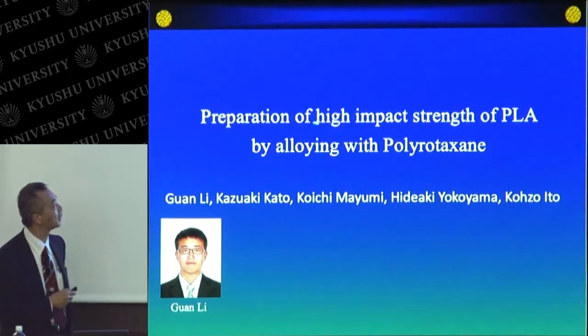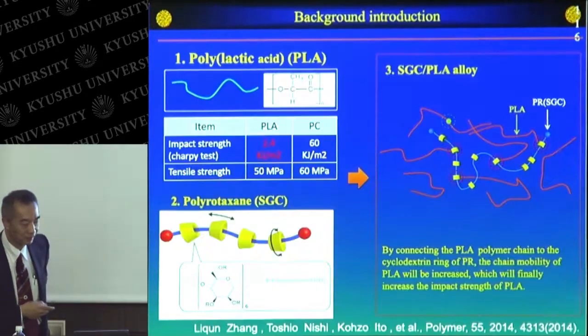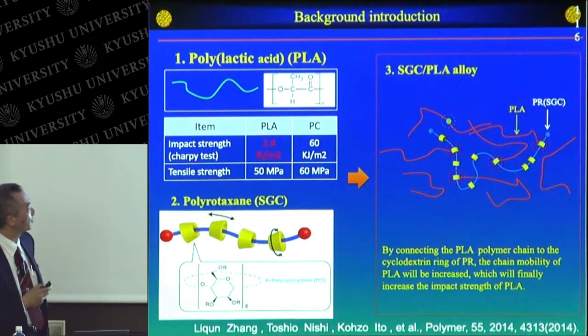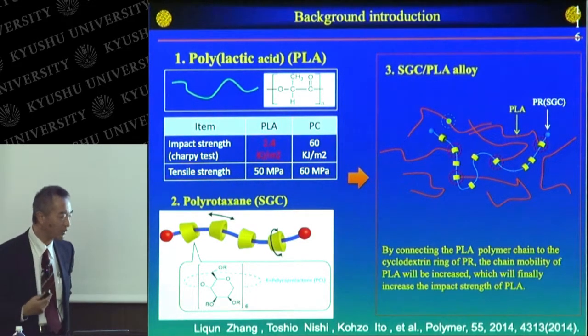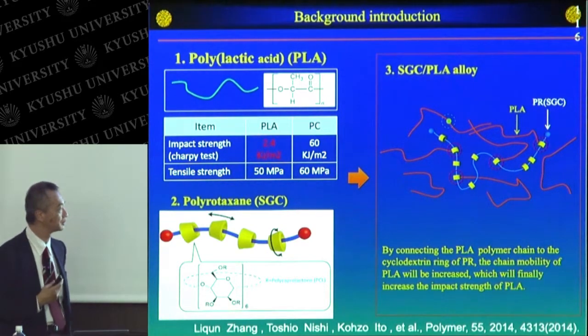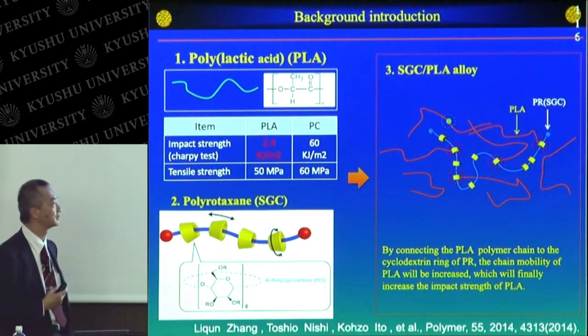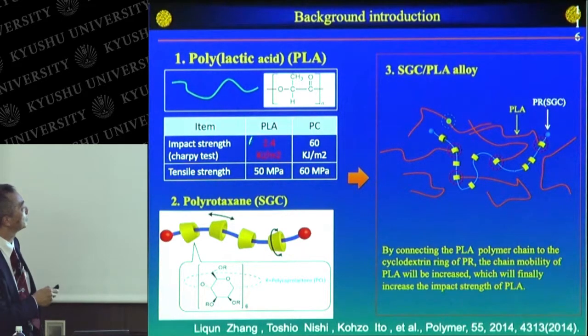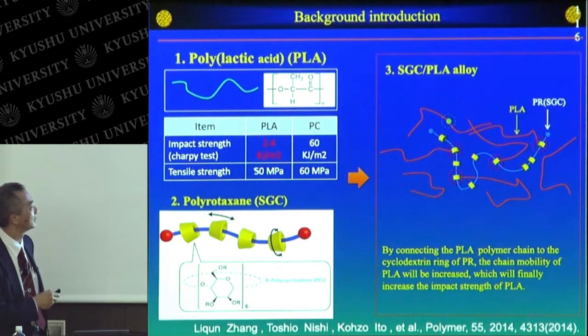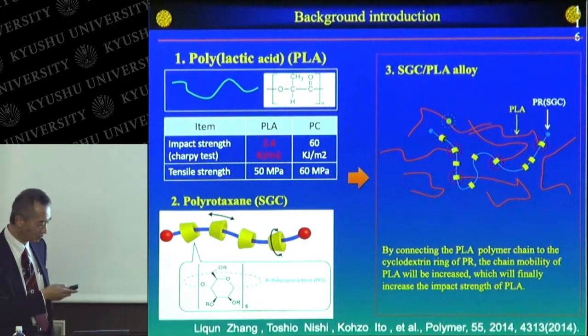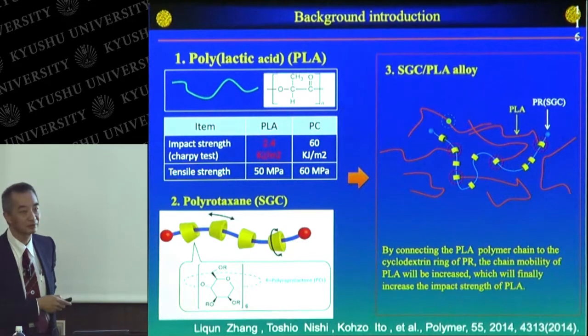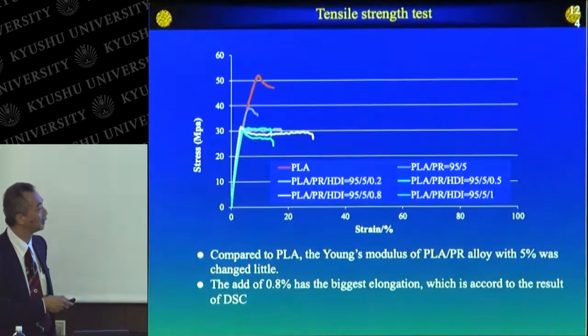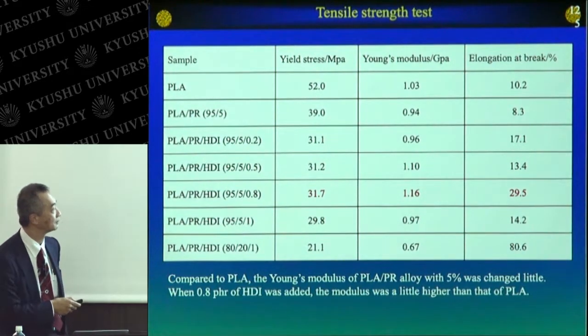Okay. So, I'd like to show you another result of the improved impact strength of the polylactic acid by alloying with polyrotaxane. In this case, polylactic acid is a biodegradable and bio-based polymer, which is very important and will be more important in the future. But the drawback is the brittleness of the polylactic acid. To improve the mechanical property, we use a small amount of polyrotaxane.